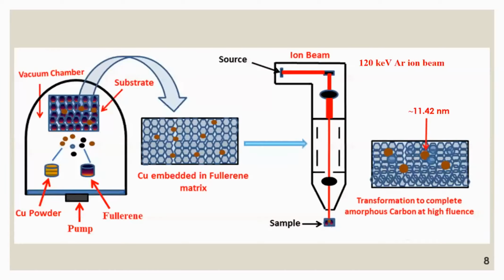This is a basic schematic diagram of what we have done. This is the vacuum chamber, our thermal evaporation unit. We have placed copper powder and fullerene in different tungsten boats, and we have evaporated and synthesized our CuC60 nanocomposite thin films. After that, we irradiated them with the 120 keV Ar ion beam. And we have observed that the size of the particles has increased from 5 nanometers to 11.42 nanometers.